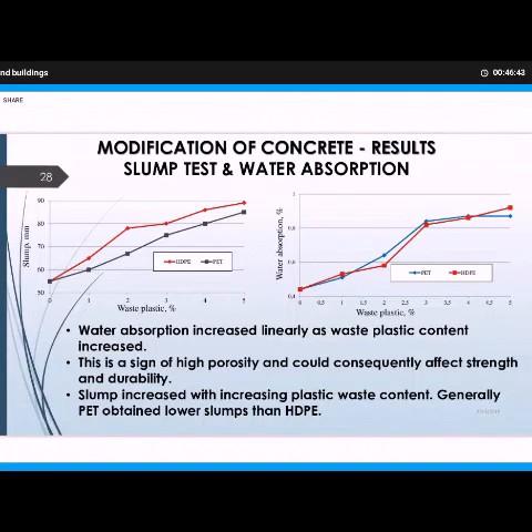So you want to be sure about the right amount of water to be used, especially if you are adding a foreign material such as the waste plastic. And so, as you can see from the slump test, it is observed that slump increased as the waste plastic content in the concrete increased from 0 to 5%. You could tell that when nothing was added to the concrete, the slump was around 55, but when it was replaced with 1, 2, 3, 4, 5% of the waste plastic, the slump increased. This is an indication that when you add plastic waste to the concrete, you need to check the amount of water, because you may have to reduce the water as you increase the waste plastic content.